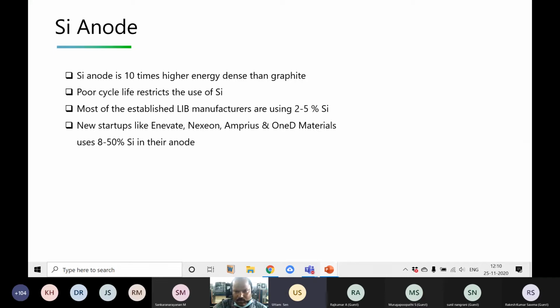So just look at the silicon. Silicon has 10 times higher energy density than graphite. Okay, but it has a very poor cycle life. But still people are using it. If you see most of the present lithium ion battery manufacturers, they are using 2 to 5% of silicon, so it's improved the energy density by around 5 to 10%.